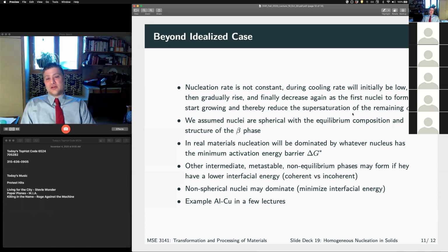We also assumed here that nuclei are spherical with the equilibrium composition and the structure of the beta phase. But in reality, nucleation is going to be dominated by whatever nucleus has the minimum activation barrier, right? We'll see this when we talk about heterogeneous nucleation, that sometimes we get special orientation relationships that develop, right? And so we get non-spherical particles because of that, which have a lower activation energy barrier. This also we'll see when we look at aluminum in just a little bit.